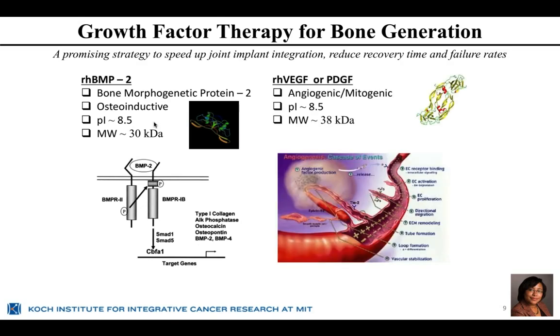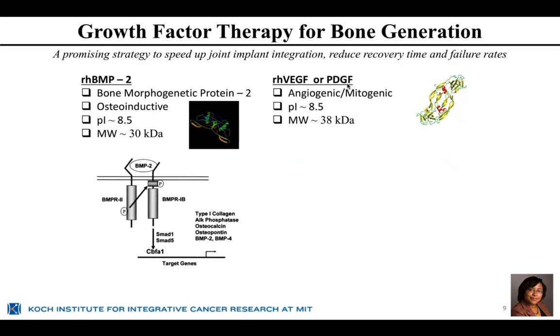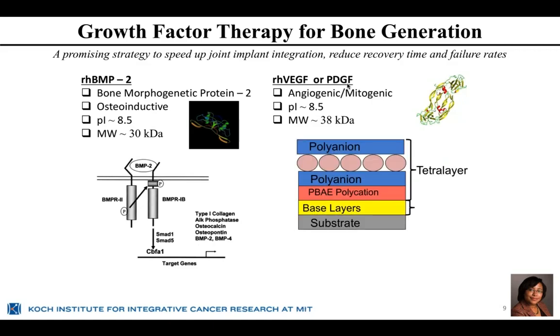We're also interested in other kinds of growth factors, ones that can help build the vascular system, like these two here, vascular endothelial growth factor or platelet-derived growth factor, both of which help support the development of the vascular system. When we generate these growth factors into layers, we treat these proteins as positively charged species, essentially as polycations, because their isoelectric points are 8.5. So at pH 7, they can be treated as weakly positively charged materials that can be incorporated into a film that has a tetralayer composition.